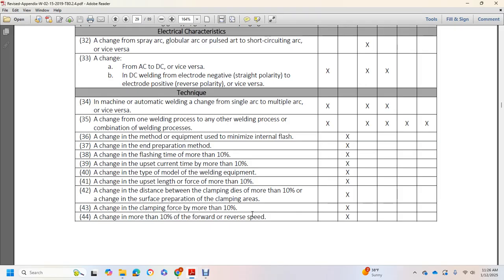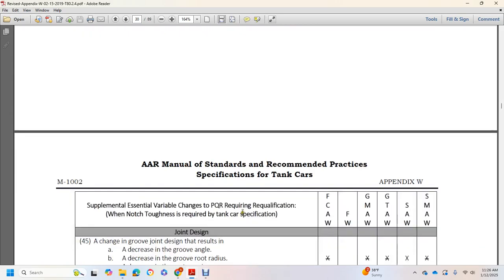A change in the method or equipment used to minimize internal flash, or a change in the end preparation method. Change with flashing time more than 10%. Change with the upset current time more than 10%. Change with the type or model of the welding equipment. Change with the upset length or force more than 10%. Change with the distance between the clamping dies more than 10%. Or change in surface preparation of clamping areas. 43. A change in clamping force by more than 10%. 44. A change of more than 10% of the forward or reverse speed, and that's in technique.